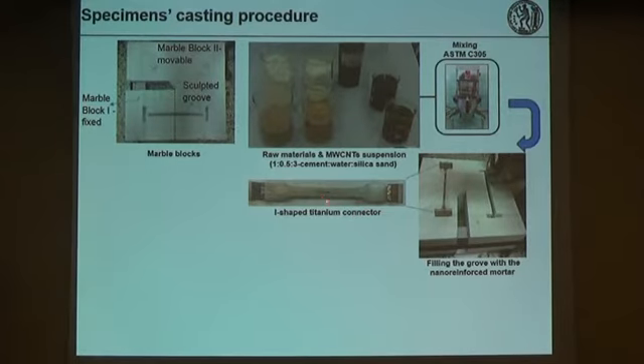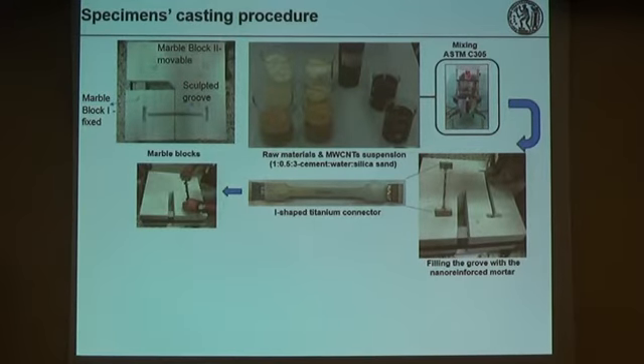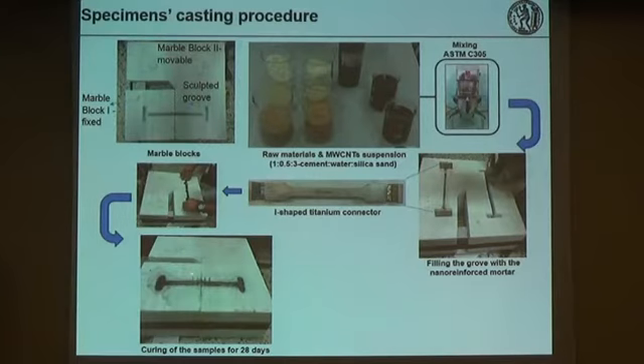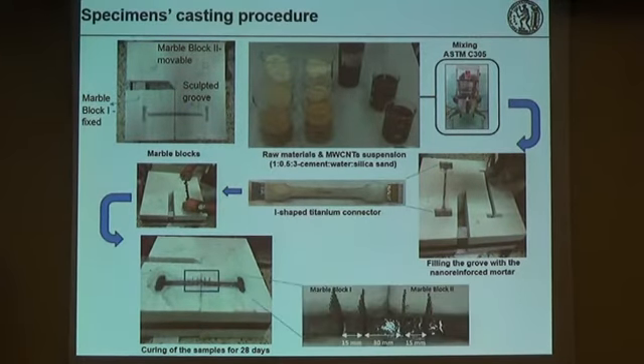Please note that on the surface of the connector we placed three strain gauges, one at the fixed marble, one at the interface of the two marble blocks, and one at the movable marble. This is the placement of the connector. We filled up the groove with the nano-reinforced mortar, and immediately after casting we placed 4 electrodes inside the mortar in order to use them for the measurement of the electrical resistance. And we cured the specimens for 28 days.